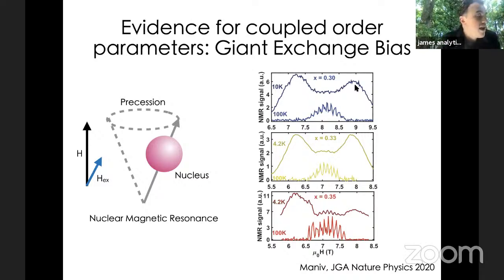So from these kinds of local measurements, we don't seem to see multiple environments that the magnetic ions see. We just observe that every moment has the same kind of environment. So from these measurements, we don't have any evidence of macroscopic inhomogeneity. It seems that all the moments have the same local environment.